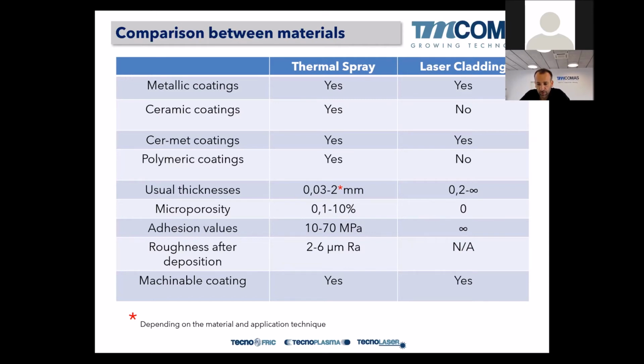Roughness after deposition in thermal spray is 2 to 6, 2 to 10, depending on the application and the gun. In laser cladding, we are not spraying, so we're not talking about roughness, because we have an as-clad weld surface, which is not useful for any grip application. It's just ready to be machined, and that's it. We don't usually leave the surface as clad. Machinable coatings, in both cases, yes. Depending on the hardness, no, but we can even grind with diamond tools. So more or less, in both cases, the coatings or the layers can be machined.